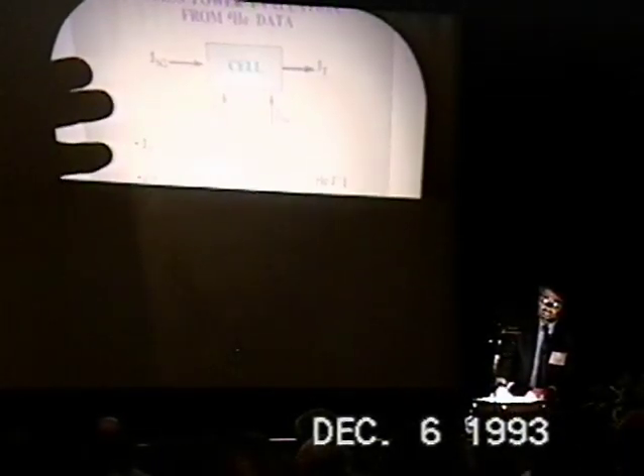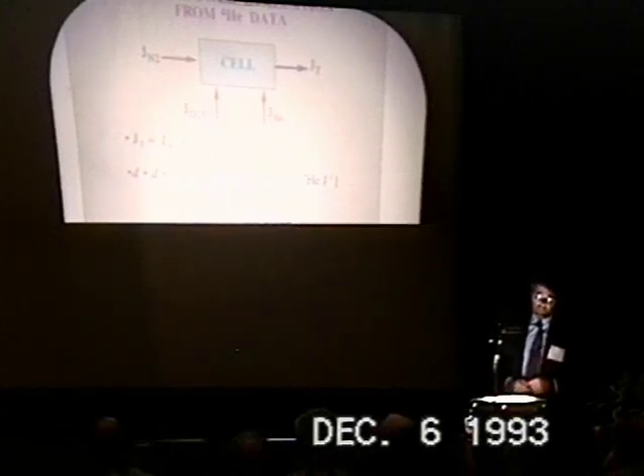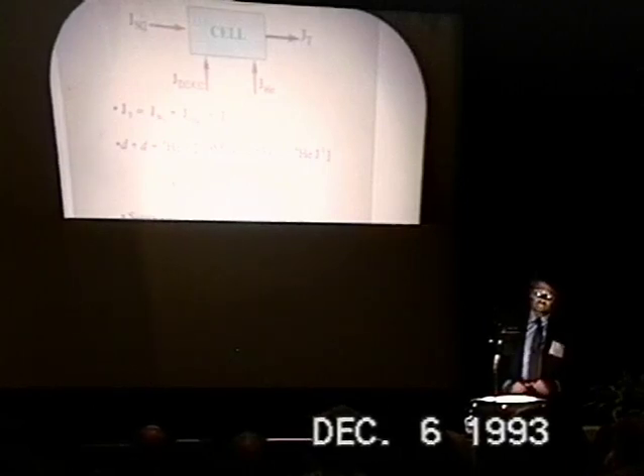To compare the calorimetric measurement and the helium-4 data, it's necessary to make a mass balance in our cells. In our cell we have nitrogen coming from liquid nitrogen, which acts as a carrier gas, and the cells produce oxygen and deuterium by electrolysis, and eventually helium-4. So, the atomic helium-4 fraction in the cell is given by this relation. B is related to the flux of carrier gas, and eta is the yield of recombination of a catalytic recombinator.